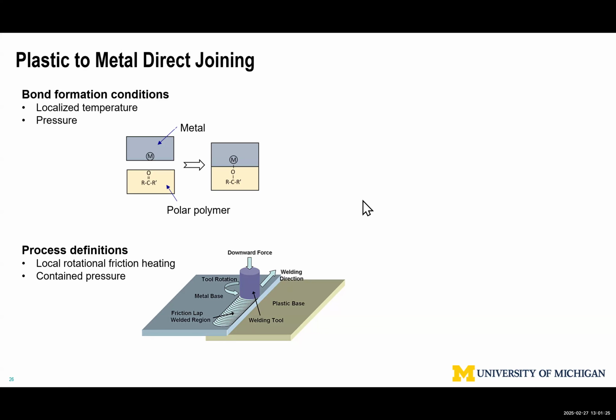Very simple. And you can use induction, other means, but you cannot put this into a furnace and then pressurize it because you violate the localized condition. Because you need the support. What happens if you heat it up? This plastic becomes so soft, it just comes up. You need a surrounding support. This little flat surface tooling worked very well. We are in the process of understanding the chemistry process.